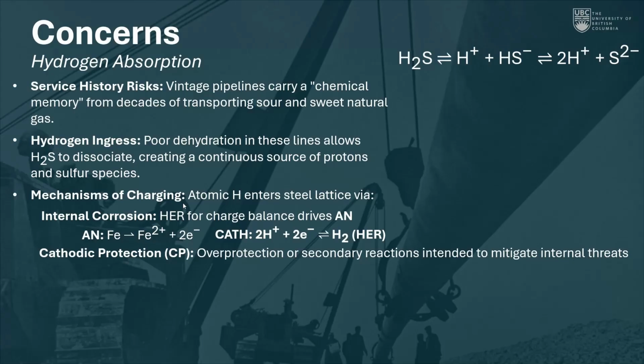And then, of course, cathodic protection is also an issue. So, of course, if the intention is to protect our pipe, if we apply negative potential or negative current, and if there are areas or pockets of moisture within that pipe, during cathodic protection we're also essentially driving that cathodic reaction. We're driving hydrogen evolution. And so we might also see further generation of hydrogen atoms within the steel.